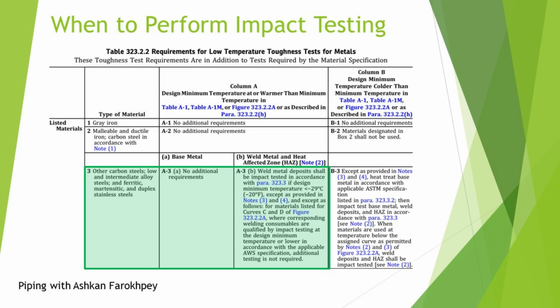By meeting some conditions, the impact test might be relaxed by the designer of the project. Some of the conditions are such as: 1. Using qualified welding consumables by impact testing at design temperature. 2. When there exists some dimensional limitation on the impact test specimen. Or when the stress ratio is below 0.3 and the design temperature is warmer than minus 29 centigrade. You can read all the notes in ASME B31.3 code to understand all the conditions where impact testing of the